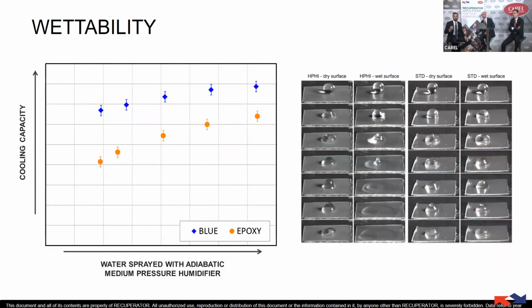And now we can see the increase of performance thanks to the blue coating, the blue dots, compared to the epoxy dots, that is the gold epoxy protection that is hydrophobic. On the right, a picture that explains the formation of the film on the plate. On the left, we can see that the droplet completely disappears on the surface. This is the blue hydrophilic absorption coating. On the right, instead, we can see the hydrophobic epoxy protection where the droplets don't disappear, they still remain droplets, as we have seen in the video. These images are very clear and show a remarkable difference between these two things.